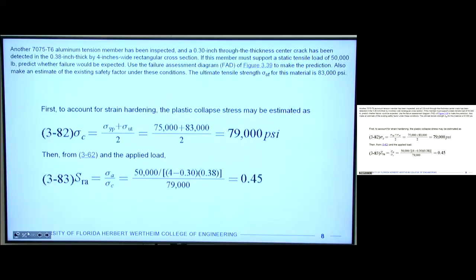Another 7075 aluminum tension member has been inspected, and a 0.3 inch through-the-thickness center crack has been detected in the 0.38 inch thick by 4 inch wide rectangular cross section. If this member must support a static tensile load of 50,000 pounds, predict whether failure would be expected.